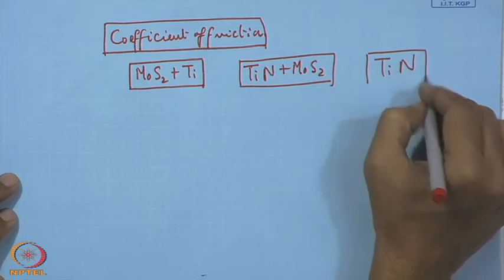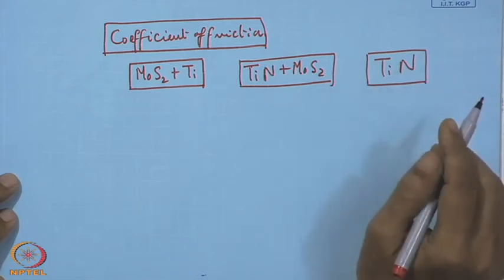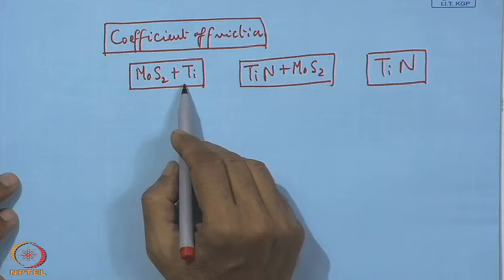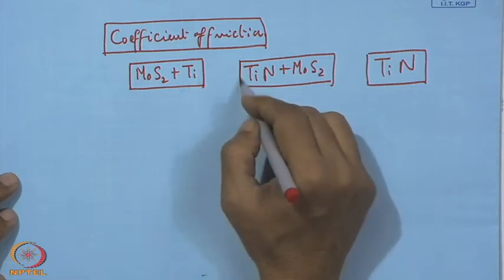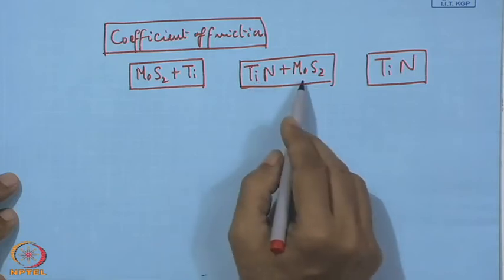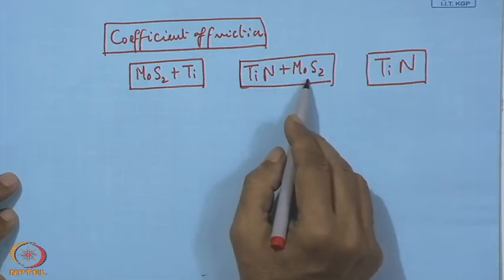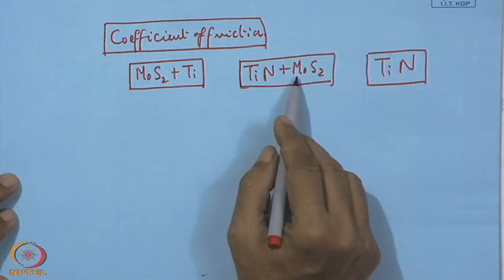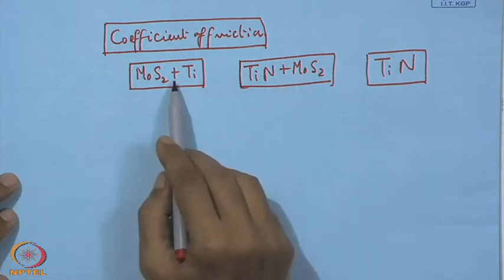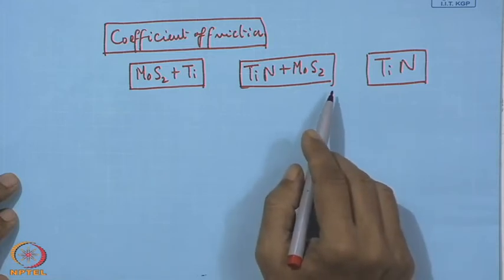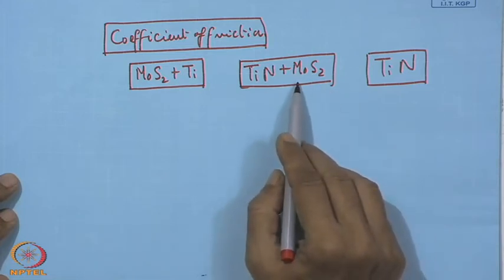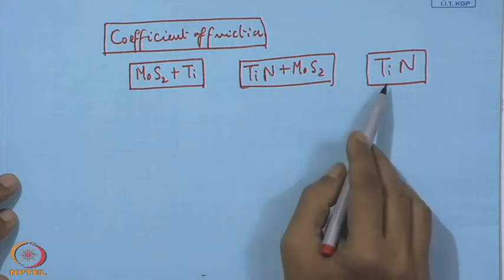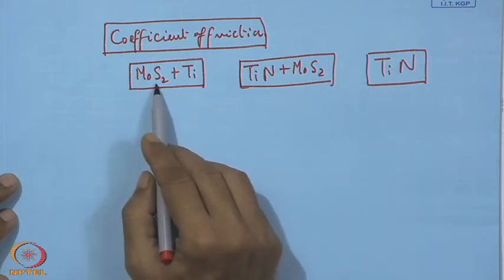However, if we like to consider both wear resistance and coefficient of friction, then the right blending between titanium nitride and MoS2, that would be one of the right choice in that direction, and accordingly that coating can be ranked as number one in this family, which can give a hard-lubricious property, and this means the hardness of the titanium nitride and also the lubricity of molybdenum disulfide.